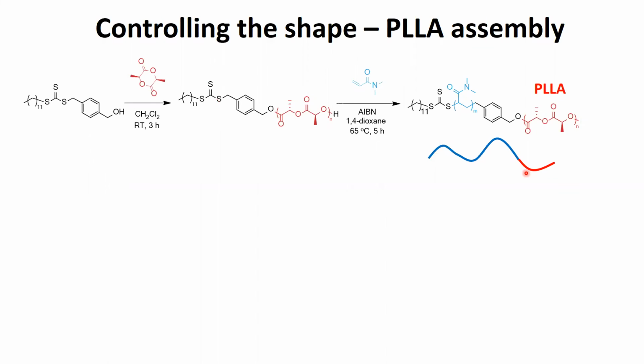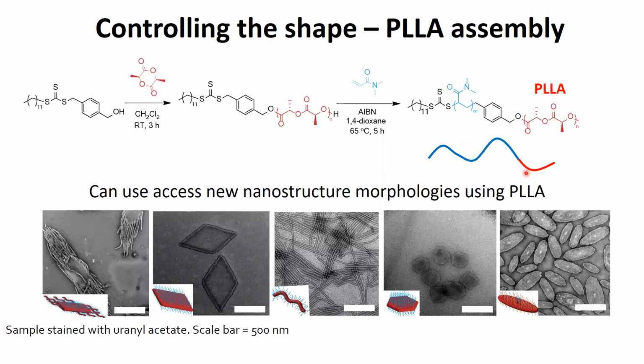And if we take this polymer, dissolve it in water, heat it up, and then cool it down and allow it to crystallize, we can form all kinds of really interesting and different shapes from this one polymer by changing solvent, etc. So this just shows you some of the different shapes we can obtain, and we can make these lovely diamond structures. And this scale bar is about 500 nanometers. So we make these big diamonds, these long rods, we can make hexagons, we can make just plates, we can make these weird kind of plates with hair, like hairy plates, etc. And all these morphologies are a result of the stereochemistry. So for a very simple polymer, we can use crystallization and stereochemistry to access these really complex shapes.